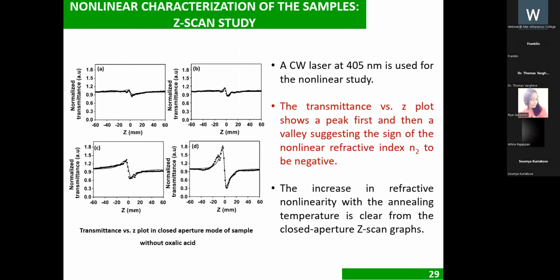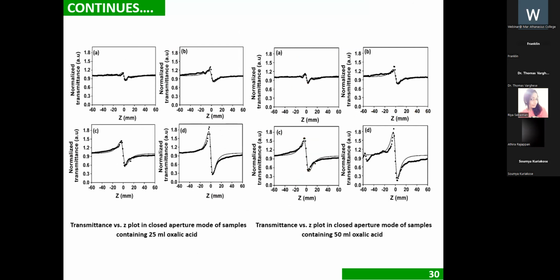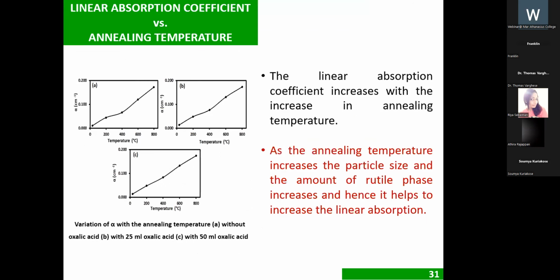Then the nonlinear characterizations were carried out by the Z-scan technique, and the variation of normalized transmittance versus Z is here for all the samples. In all cases, a negative nonlinearity is visible because there is a peak which is followed by a valley in all cases. How the linear absorption coefficient, alpha, varies with annealing temperature is plotted here.